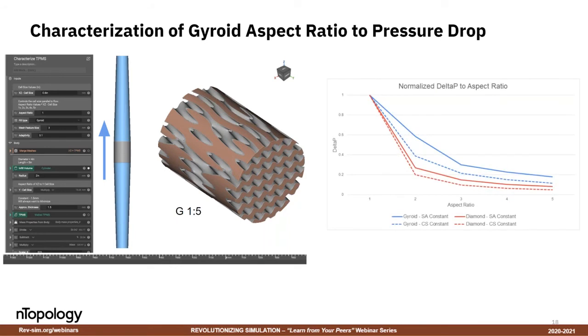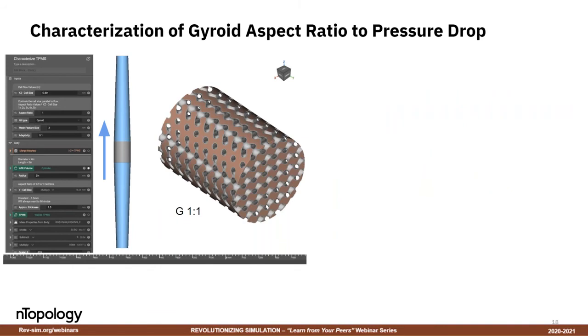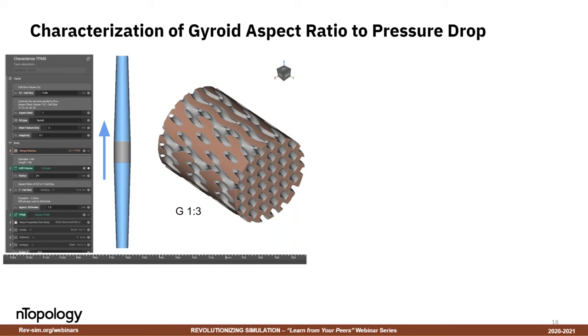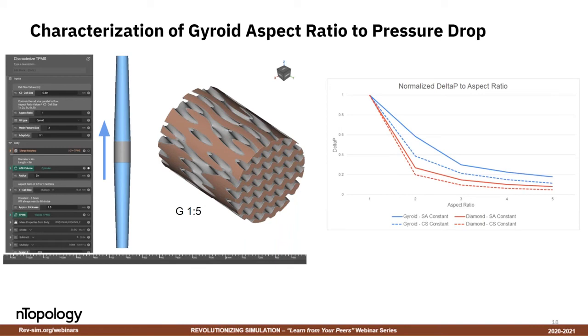At some point, we want to find out, because, let me backtrack a little bit. We see pressure drop increases the further fluid has to travel through a structure, right? So yes, we get a lot of increased surface area, but at the same time, we might also have a significant amount of pressure drop. So at what point can we find a balance between aspect ratio and surface area? And we were able to do that with the short design study.